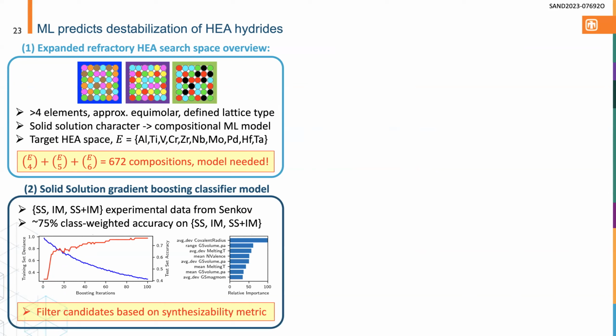So because we're working with solid solutions, we don't want to just predict any random composition, of course. We want to make sure that composition is likely to actually form a solid solution. Luckily, Miracle and Senkov, who are some of the founders of the high entropy alloy field, published this really nice review where they summarized which experiments have been able to isolate solid solutions of these particular compositions. The negative examples are where they crashed out into intermetallics, or there was some phase impure mixture. So you can, again, train something like a gradient boosting classifier to get within a 75% class weighted accuracy, whether a particular composition is likely to form a solid solution.